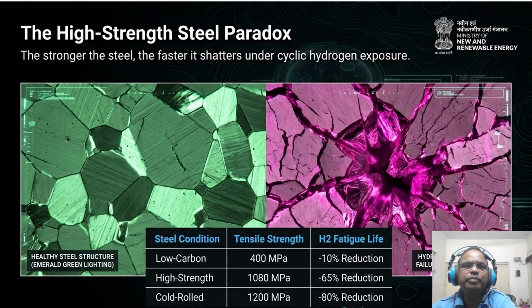Now look at the table. Low carbon steel at 400 MPa sees a 10% fatigue life reduction. But move down to cold rolled steel at 1200 MPa, it suffers a staggering 80% reduction in life.